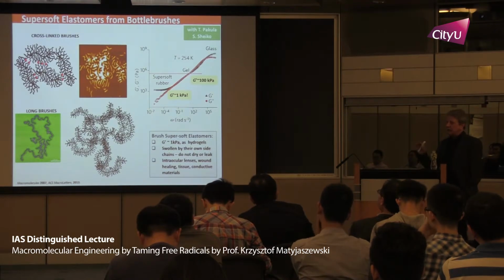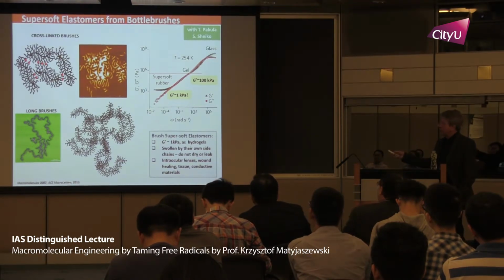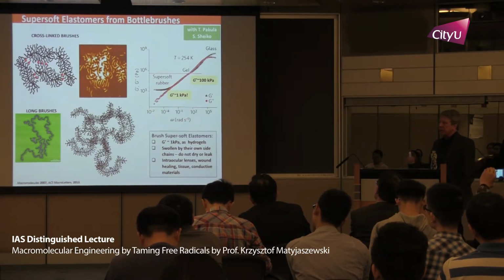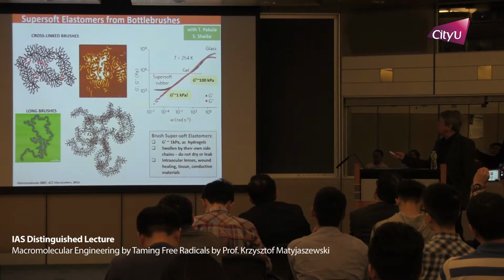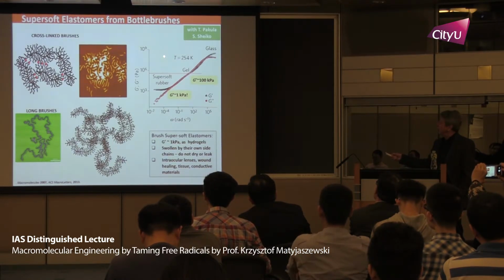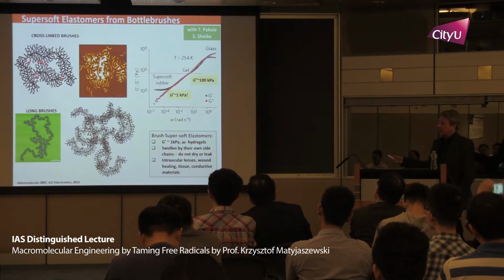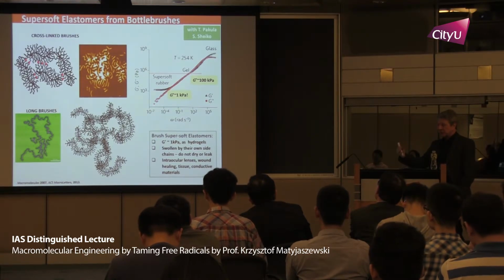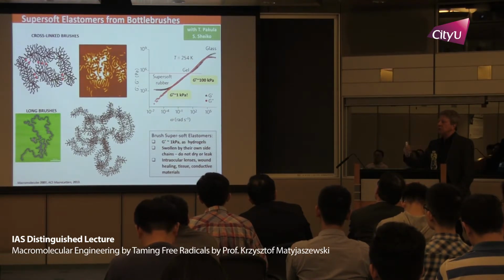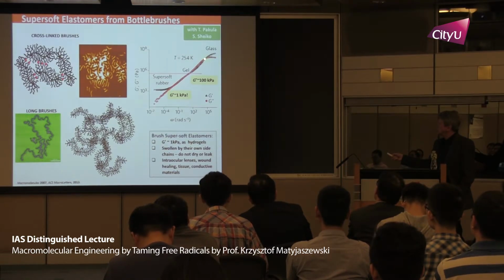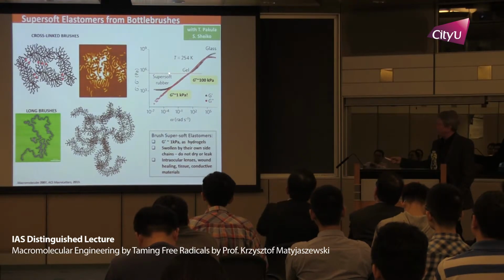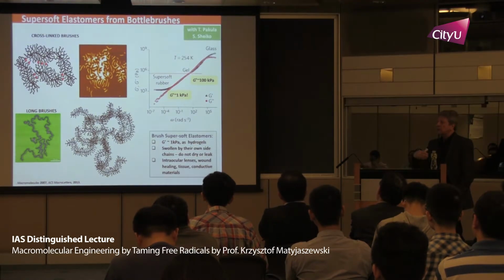So if you take any polymeric material below glass transition temperature, it is very hard. So when you think about plexiglass or polystyrene, it has a modulus of stiffness around 1 gigapascal. And then if you go above glass transition temperature, this polymer starts flowing. And modulus of stiffness decreases. Then you have some kind of a rubbery plateau, and then the system flows completely. You can process it by injection molding or some other techniques. So it's a rubbery-like state.